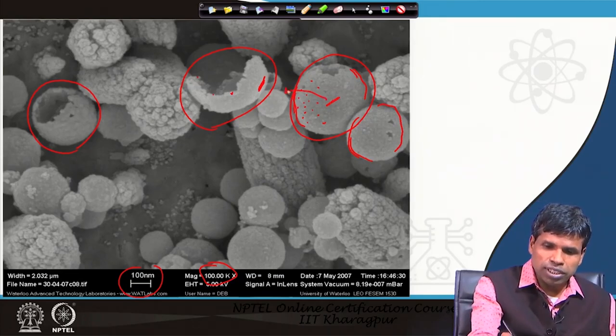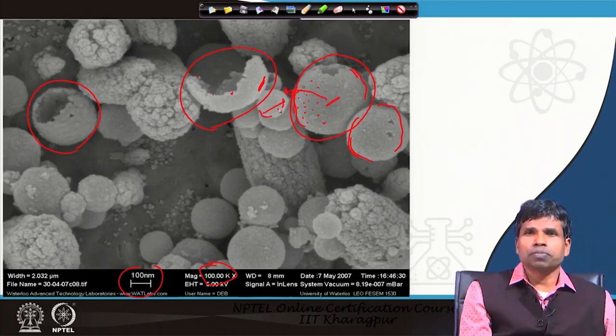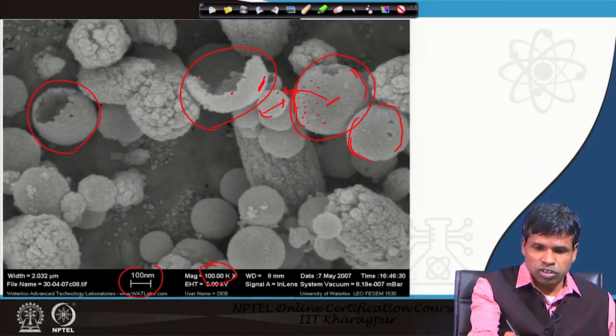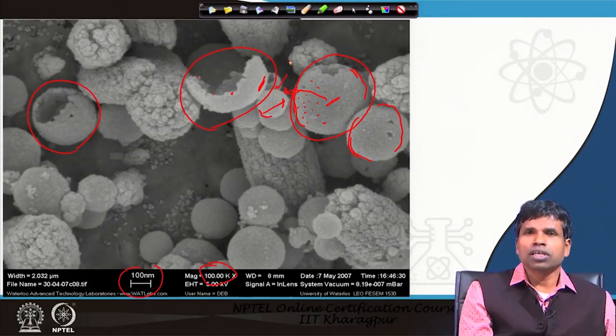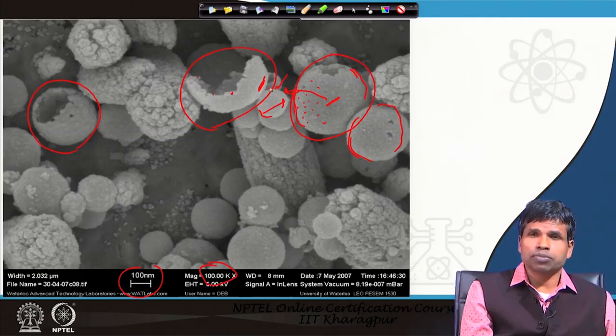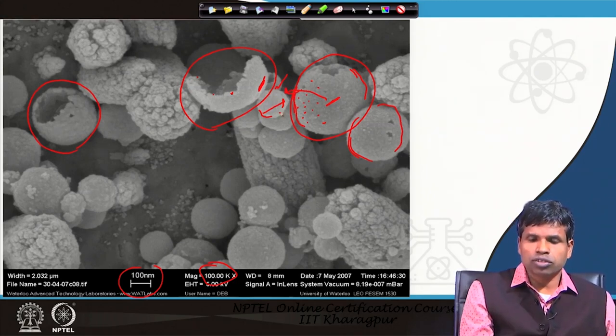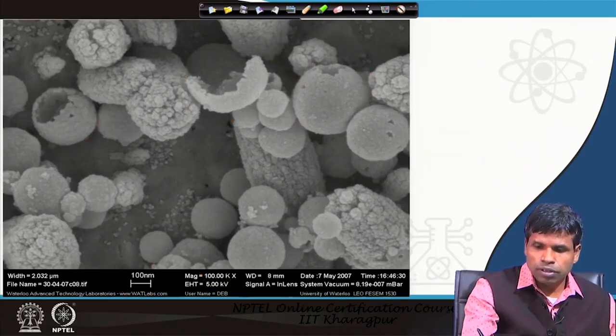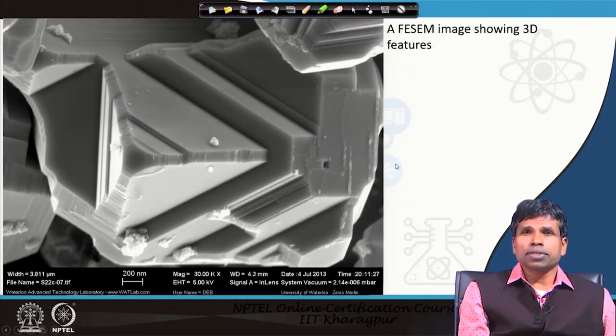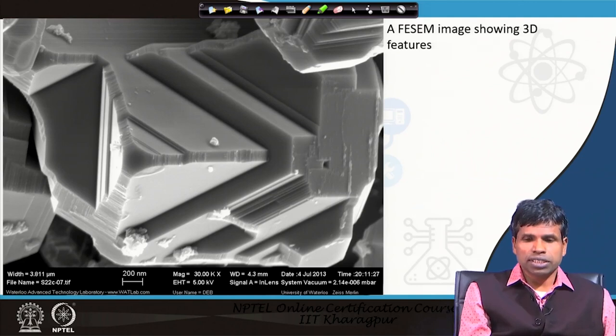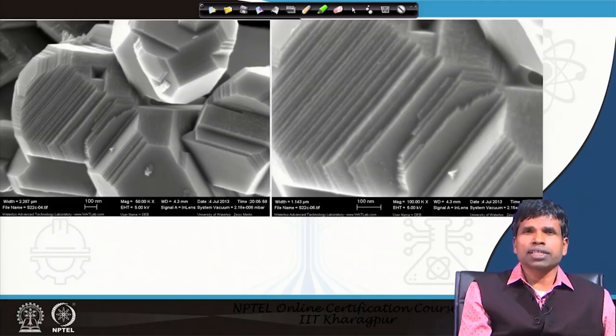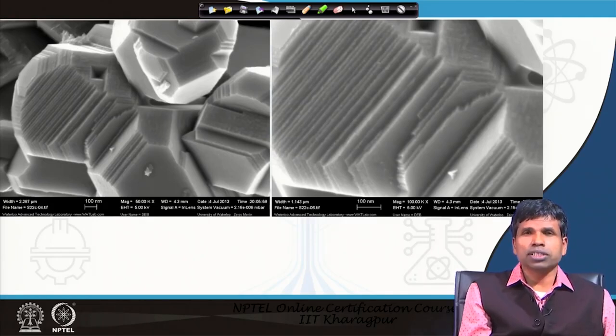Comparing spheres: if the brightness is almost equal across the diameter, this indicates that the sphere is either solid or the thickness of the wall is higher — when thickness is more, brightness will be more uniform across the sphere, with only a little higher brightness at the edge. Here you see another three-dimensional image showing different steps and different sizes of a sample at higher magnification, with steps measured at the nanometer level — all three-dimensional as viewed by the scanning electron microscope.